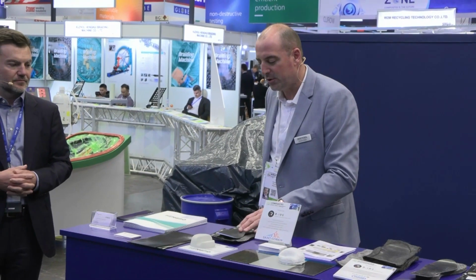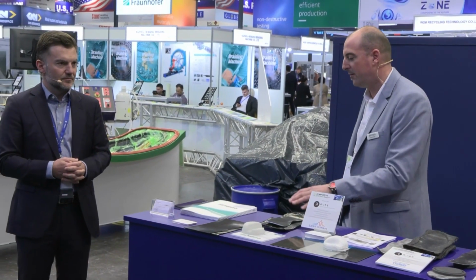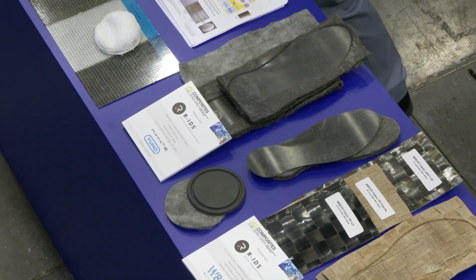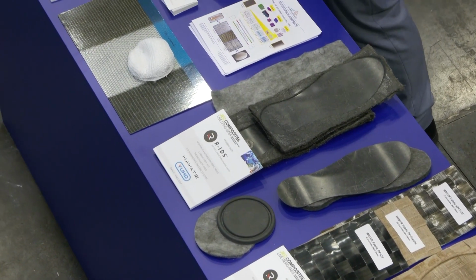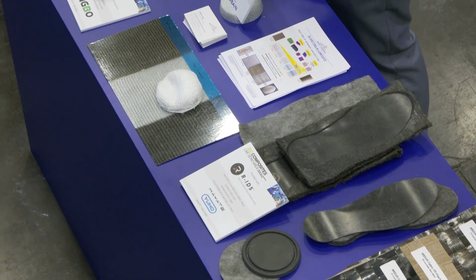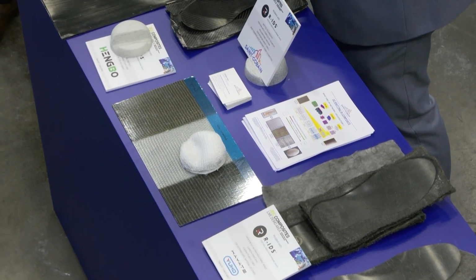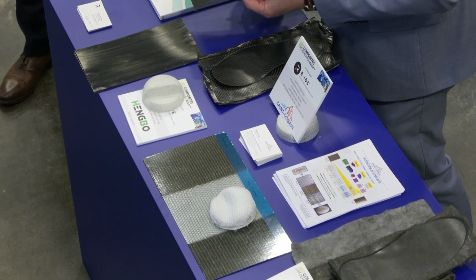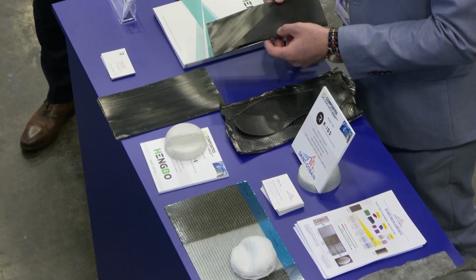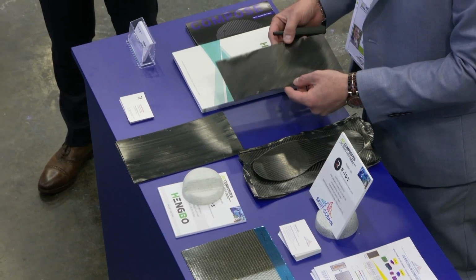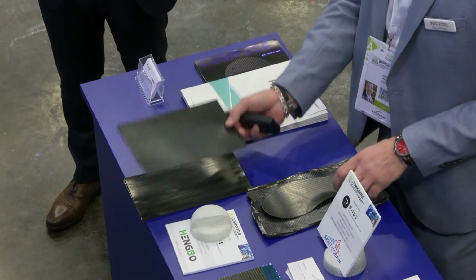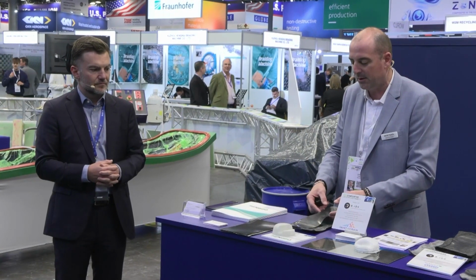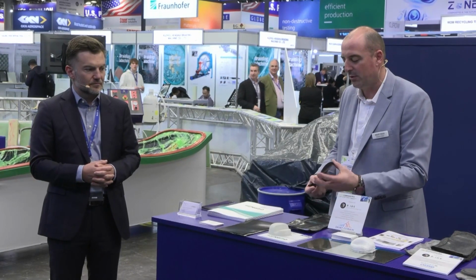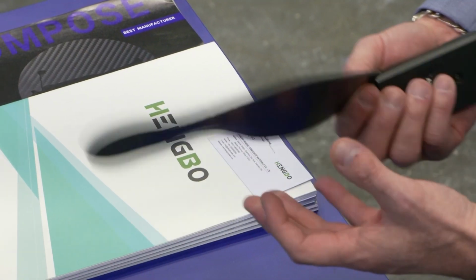We also show you material from the Hengbo company. It's a Chinese company. They produce prepreg material with, in this case, nylon resin. It's a carbon weave, but they also have a range of unidirectional carbon fibers. For this application, yesterday we showed a shoe sole mold, and we used these different configurations to produce this sample.